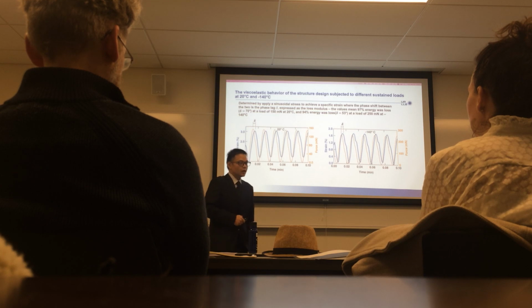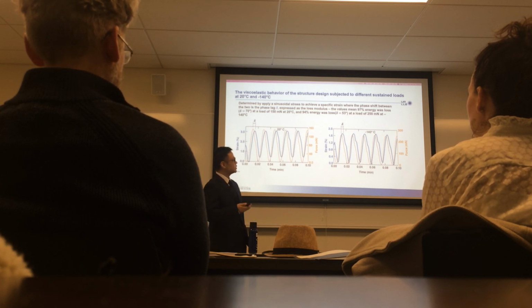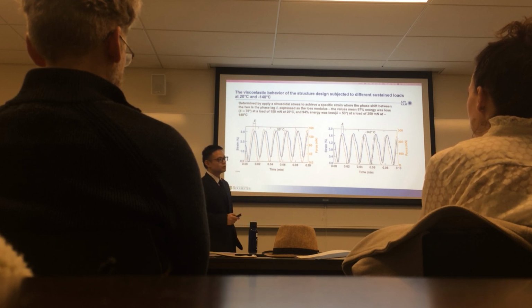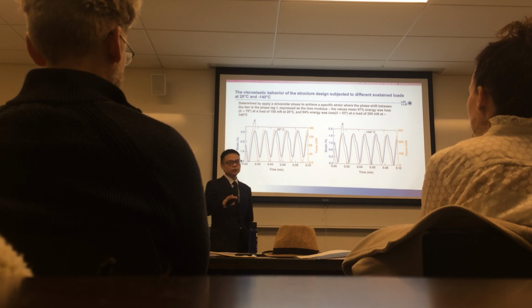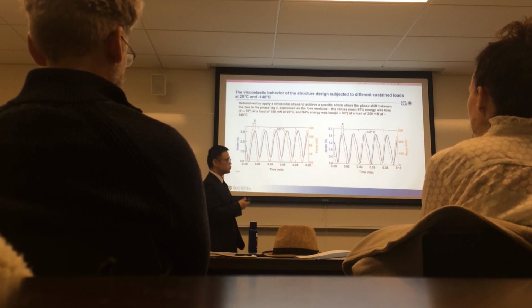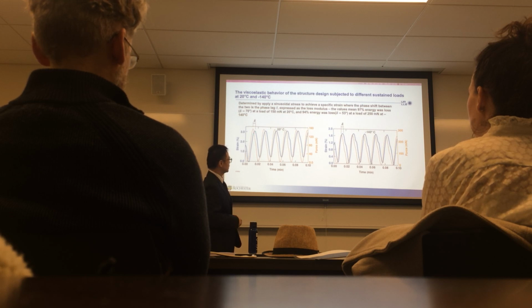Okay. After we designed a better generation foam structure in the crush test, we tested this foam structure in the repeating loading test. This repeating loading test is like applying some cyclic force on the foam structure. So the foam structure will experience cyclic strain, and I measure the shift between those two curves. And from this shift, we can calculate the energy loss of the foam structure.